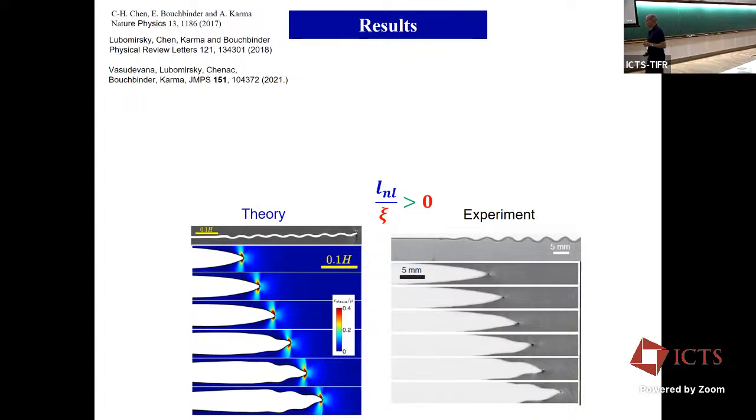That's the same reason that the crack is accelerating and accelerating. Remember, as the crack gets larger, the energy flux scales with the length of the crack. Now, 1 over the curvature actually scales also with K, this stress intensity factor, which is a fancy word for the square root of the energy flux.